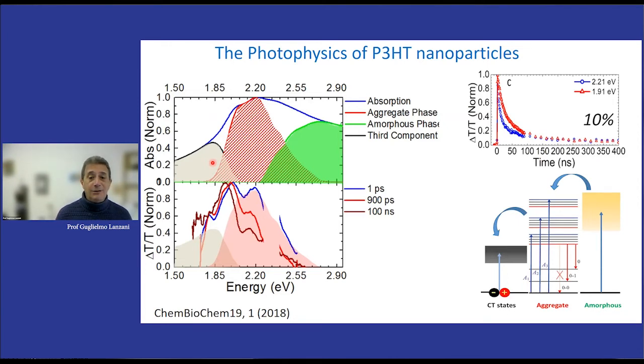What's interesting here is that when we pump with the light pulse, which is stimulating both the amorphous and the crystalline part, we see only bleaching of the crystalline part. And we also see that in time, this bleaching is moving toward lower energy. This means that following excitation, the energy quickly goes to the crystalline part, which is organized in an excitonic structure, so there are delocalized states, and eventually goes to the surface states at lower energy. This shift of the excitation is called spectral migration.